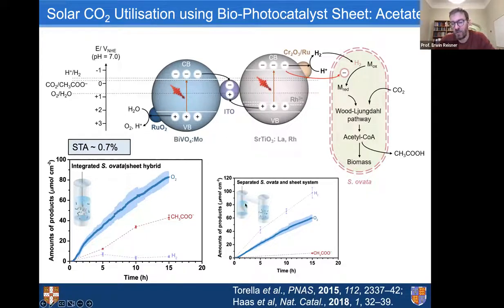And that's because now the photocatalyst sheet generates the hydrogen, and it mainly accumulates here with some diffusing to the bacteria, but the bacteria does not benefit from the high local concentration when it really grows on the photocatalyst sheets. So I like this because it shows that there's a real benefit of integrated technologies. This does not mean that these decoupled systems do not work. It just shows that really under these dilute conditions we are working at, there is an advantage of really putting